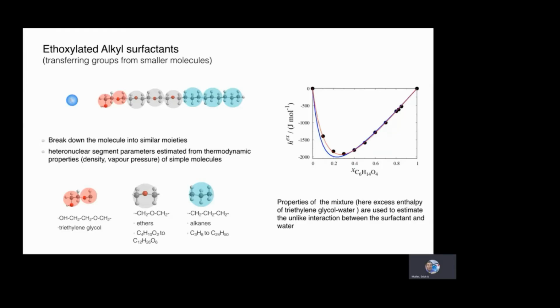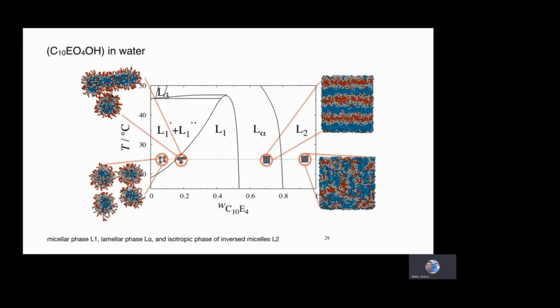It's very interesting to see that using these parameters and without further adjustment, we were able to look at the different morphologies of these surfactants in water. We went all the way from the micellar region to the worm-like regions to being able to predict lamellar phases and inverse micelles, all with the same set of parameters.